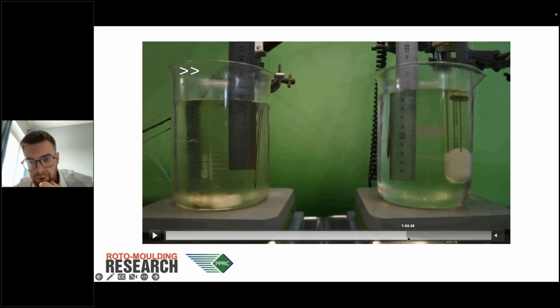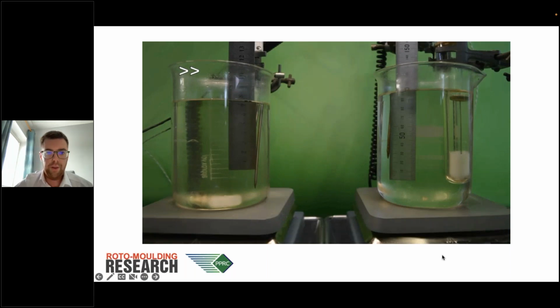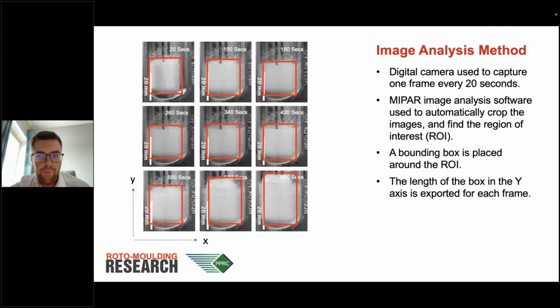And this then gives you the shrinkage of the foam during the cooling process. So from the images that were captured, roughly 1 every 20 seconds was sufficient to capture the data that I needed. The images were imported into some software called MIPAR, which automatically cropped the region of interest, so the red box in this case, in each image, and it exported the height of the box in the y-axis, which gave me then the foam height change.